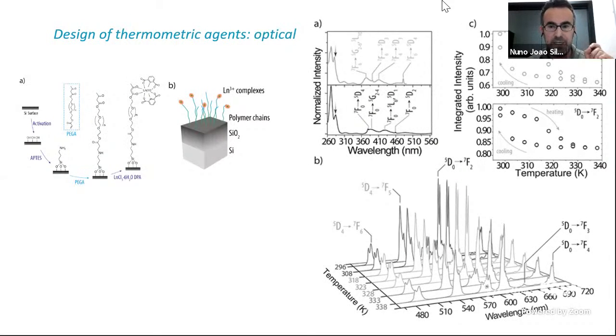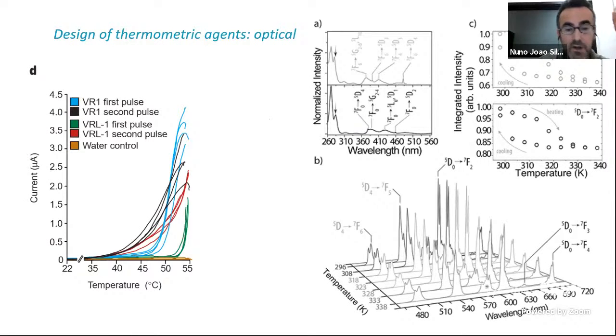We are trying to have a very nice thermometer, but in fact, we came up with something different. We came up with something where the intensity of fluorescence has not a well-defined relation with temperature. So it has this thermal hysteresis. It gives us information about temperature, but also information about the history of the system. So when we are heating up, that's the response. When we are heating, we are on this curve here, we are cooling, we are going down here. And so this is somehow reminiscent of what nature does.